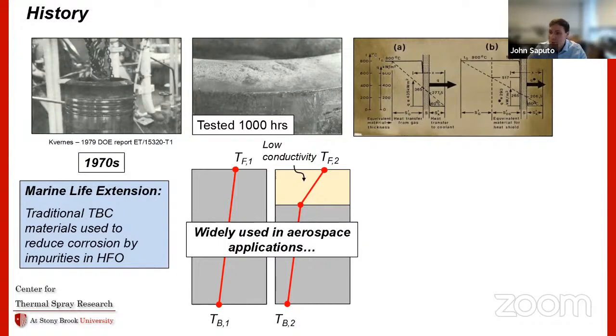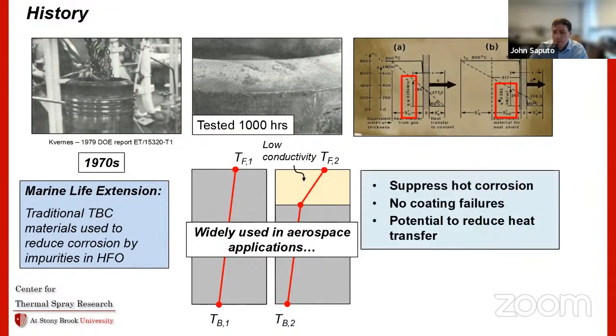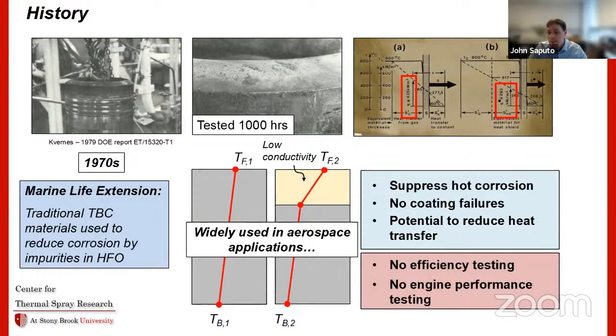So this is a dirty old piece of paper taken from a Department of Energy report. It's kind of difficult to spot in here, but I'll call out the numbers they give, where they projected a reduction in the heat flux that travels through the wall in these systems, but they didn't actually do any measurements of this. They did see it successfully suppress hot corrosion, and they didn't really see many failures in the coatings at this time. They predicted a potential to reduce heat transfer, but there's no actual efficiency testing and no engine performance testing. All they looked at was, did these coatings reduce the corrosion rate they see on pistons?